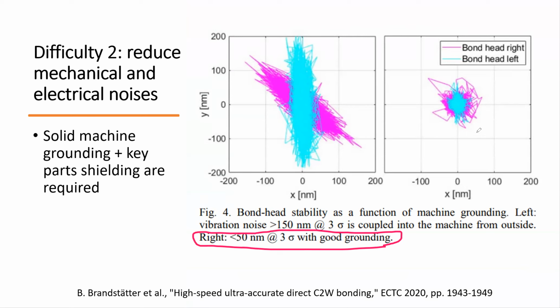So they say this is what they have. This is what I have with the noise, X and Y position. Now, if I did a good noise reduction, I got 3x better. It was 150 nanometer, and then I dropped to 50 nanometer, 3 sigma. So this is what they can improve by simply taking care of machine grounding. I myself did a lot of experiments, and grounding is one of the big concerns in many of the tools we have, because tools are so complex. And they can talk to each other if you don't take care of the grounding issue and shielding issue. Okay, so that's the control part.